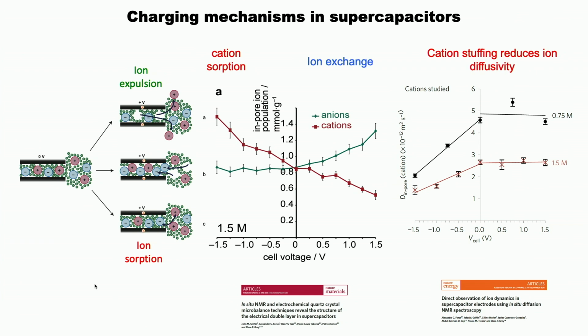And so what we did was to look at this and quantify the ions on charging to positive versus to negative. And we showed that if you charged negatively, you actually sorbed cations, whereas if you charged positively, you had an ion exchange mechanism. And then by doing pulse field gradient spectroscopy, we were able to show that if you stuff lots of cations in your material, not surprisingly, the diffusivity of the ions inside these pores went down. And so the moral of the story was, if you want to get high rate, you want to avoid these types of carbon sorption processes. You want to have an ion exchange process so that you can still move the ions.